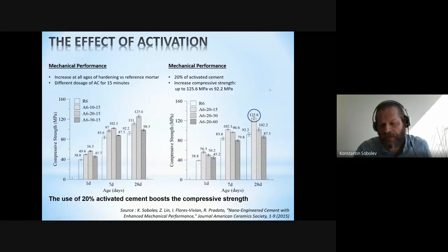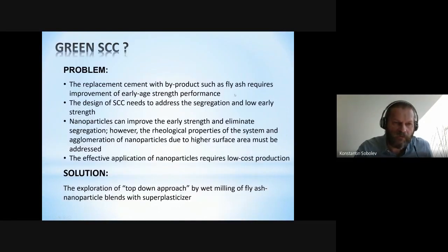we don't use silica fume here. We use superplasticizer, and we use a very small quantity of nanosilica for activation, just as a process in viscosity modifying admixture. So this is considerable improvement which we can use for production of self-consolidating concrete.